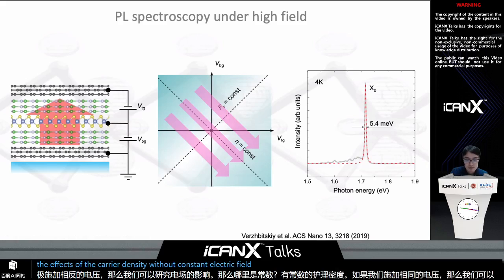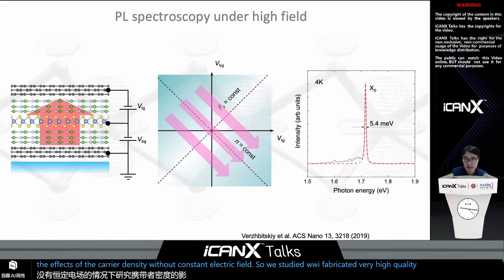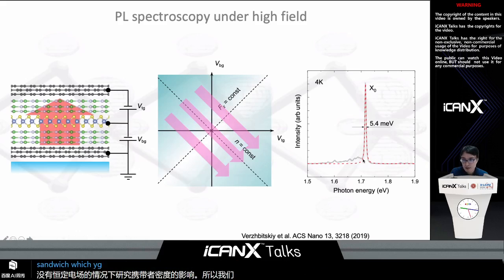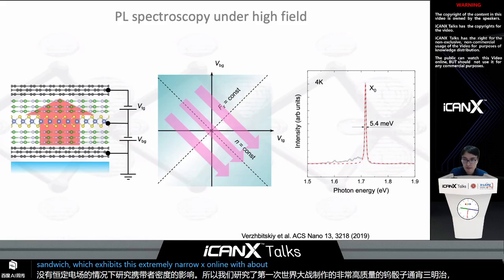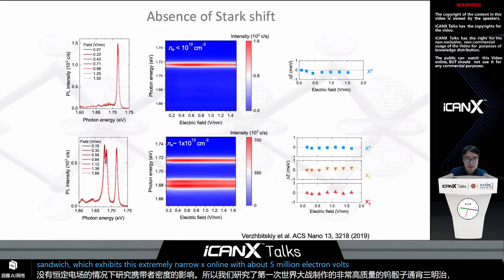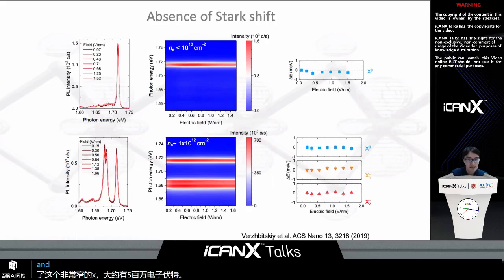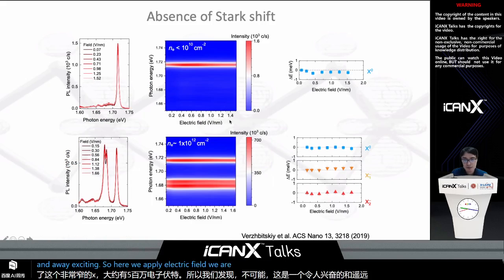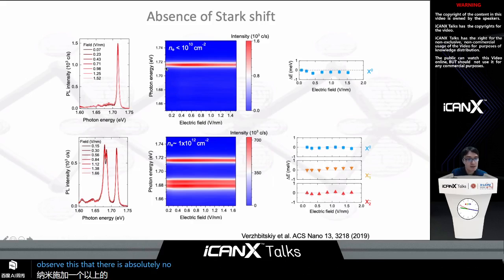So we fabricated a very high quality tungsten diselenide sandwich, which exhibits an extremely narrow exciton line width of about 5 milli-electron-volt. What we found was in a way unexciting and in a way exciting. When we applied the electric field, up to more than 1 volt per nanometer, what we observed is that there is absolutely no shift in the exciton resonance.